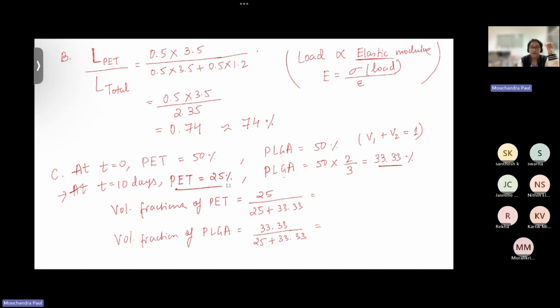This will be the numerator divided by the total polymer, how much it will experience load. And we are using the values for elastic modulus only, because elastic modulus is directly proportional to the load, or vice versa. Load is directly proportional to elastic modulus. So in this way, we are calculating that 74% of the load is experienced by PET, and the rest of the load is experienced by PLGA. So that makes sense, right? PET has a very high elastic modulus, so it can definitely bear much more load.